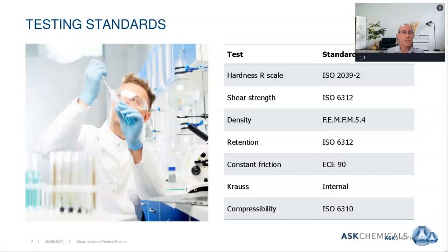This slide shows us the testing standards that we have chosen, which are well known throughout the industry, because these are the normal testing standards. In our case, we did test the hardness, as well as shear strength, density, retention, constant friction in line with the ECE 90 protocol. The Krauss testing equipment was internal equipment that we used. And then finally, we also tested compressibility of the friction compound in the matrix.